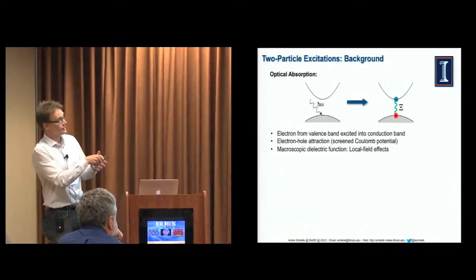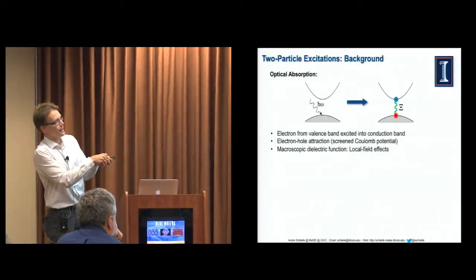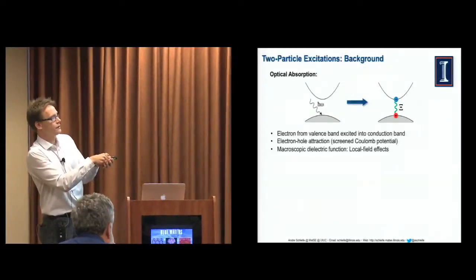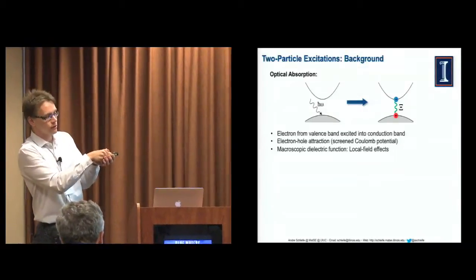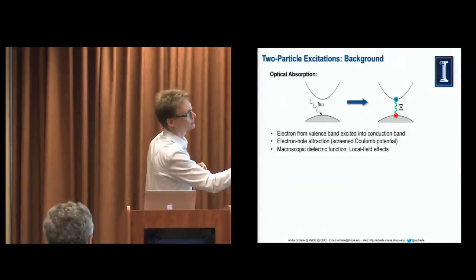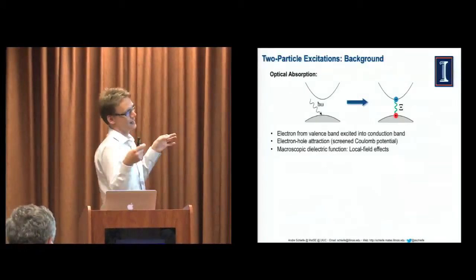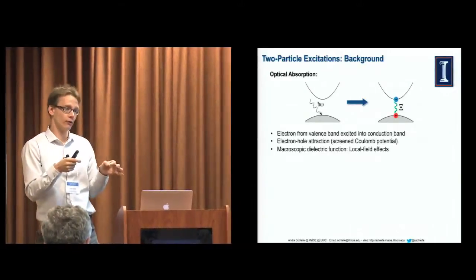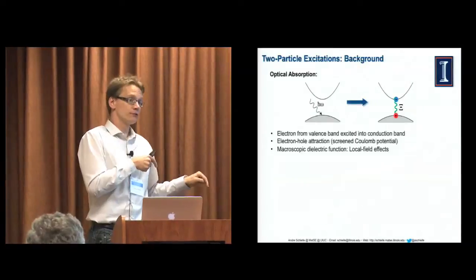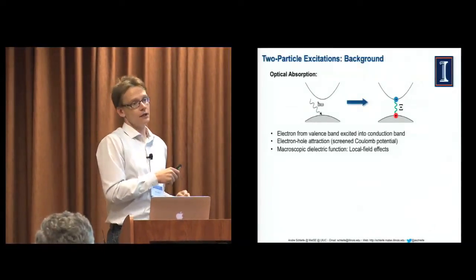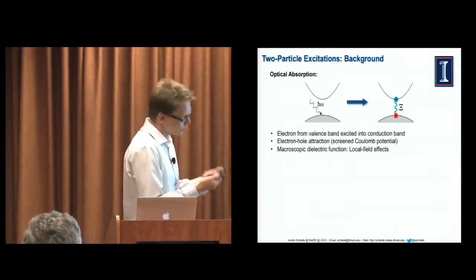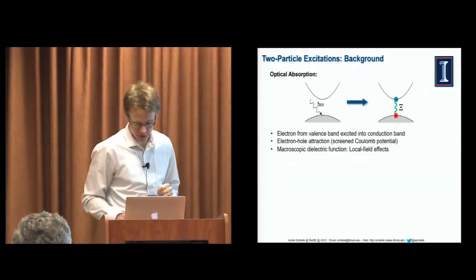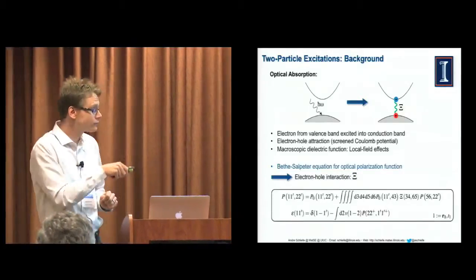The consequence of that is that this electron in the conduction band state and the hole in the valence band state, they feel each other because they're oppositely charged. So right, you can see this electron is negative, the hole is positive. This interaction has to be taken into account. None of the approaches that I mentioned so far does actually a good job doing that. And so we have to use a different approach, and in our case that's called the Bethe-Salpeter equation.